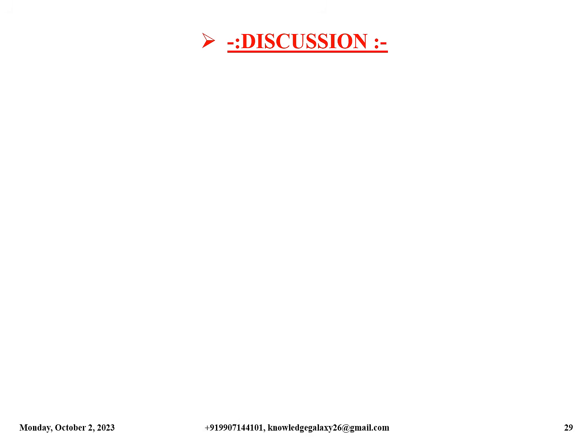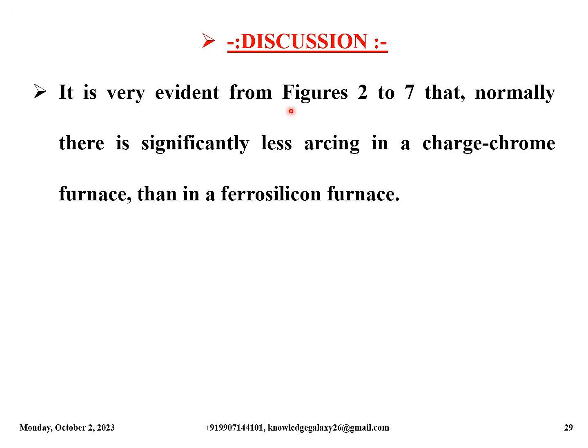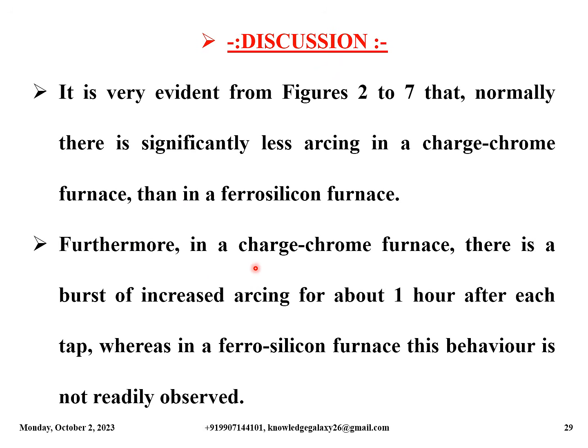So let us have some points for discussion. It is very evident from figures 2 to 7 that normally there is significantly less arcing in a charged chrome furnace than in a ferrosilicon furnace. Furthermore, in a charged chrome furnace, there is a burst of increased arcing for about 1 hour after each tap, whereas in a ferrosilicon furnace, this behavior is not readily observed.